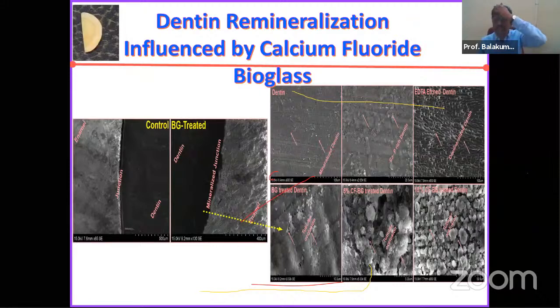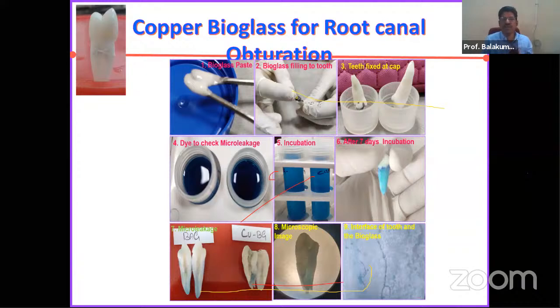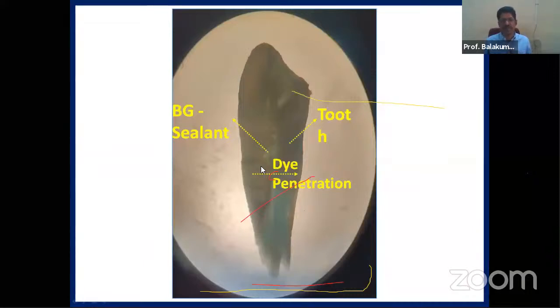Now it is being published in one of the American Chemical Society journals. Similarly, we also established the tooth filling material using this. So copper-based bioglass we have synthesized, and also we worked with SRM Dental. Then we used this as a filling material, and we evaluated using dyes, and we found that leakage is very, very low. This material is better than commercially available material. This is also used as a sealant material, and the dye penetration is very less.